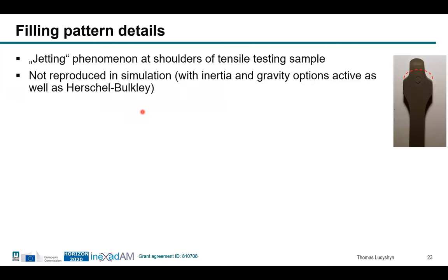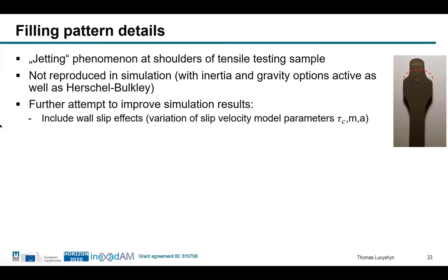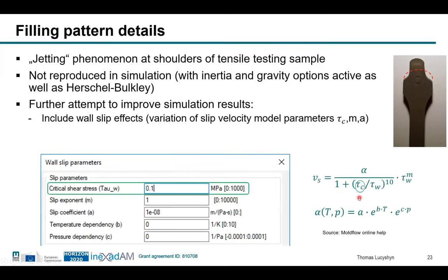considered correctly. So we tried everything that the software gives us as possibilities. We used inertia, we used gravity options, also this Herschel-Bulkley behavior, but still it was not what we expected. An additional attempt was to improve the simulation results by using the wall slip effects, which is also included in Moldflow. There are some velocity parameters in Moldflow which we can change. It's this critical shear stress, the slip exponent, and also the slip coefficient. So basically we played around with these values. We didn't have any experimental or measured values, so we just did some parameter studies that really